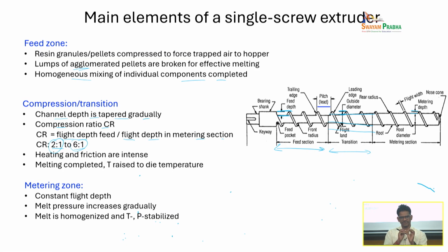And because we do this change of the dimensions, we will have intense heating and friction. Because you are forcing the material, the speed of the screw is the same. Whatever material is flowing through the feed will have to go through the other sections, but at a smaller gap. That means you are pushing it against a smaller gap, so that will increase fluid friction, that will lead to viscous dissipation, that will lead to increase in temperature, and that will lead to melting also.